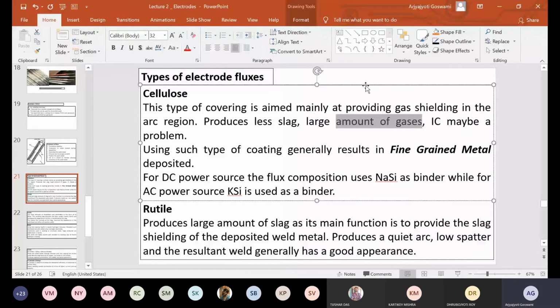But if cellulosic coatings are there, the slag will be less. Since the slag covering is not that much, it will cool very rapidly, very easily, in a very fast manner. If it cools very fast, then the weld metal will be a fine grained metal deposition. This is a characteristic of cellulosic coating. For DC power, the flux composition uses sodium silicate as the binder, while for AC power, potassium silicate is used as a binder.